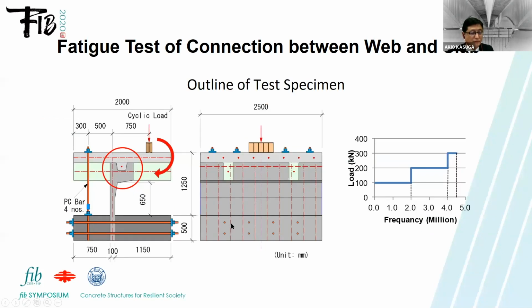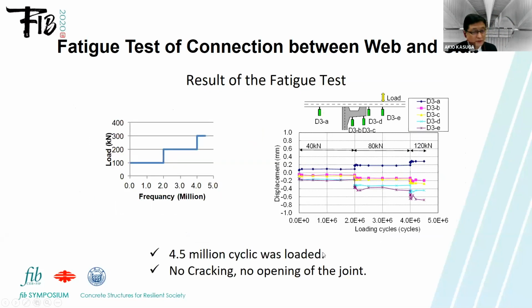We have to confirm the long-term behavior. So this is a connection detail. We have a pocket here. We arrange the aramid fiber this way and this way and this way. And in order to confirm the fatigue durability, we use cyclic loading here, from 100 kilonewton to 200 up to 300, about 4.5 million times. This is the result. Up to 4.5 million cycles were loaded, and no cracking and no opening of the joint was confirmed. And we confirmed that this detail is okay for the real structure.